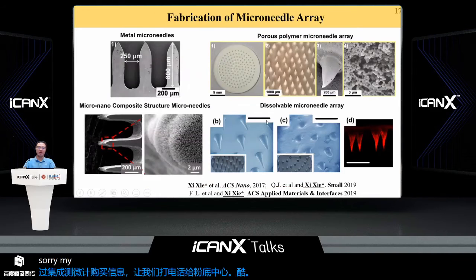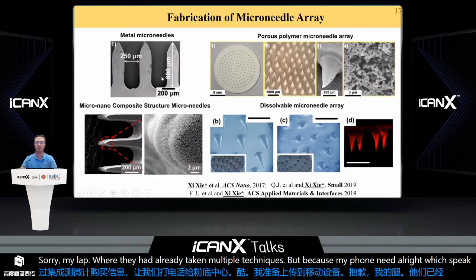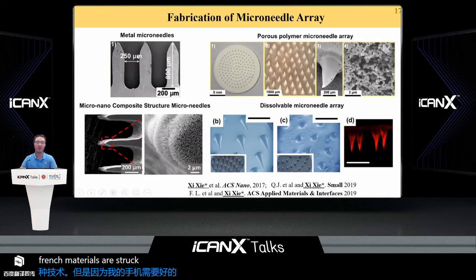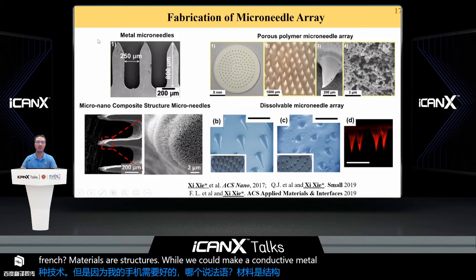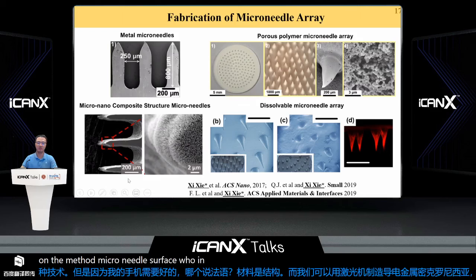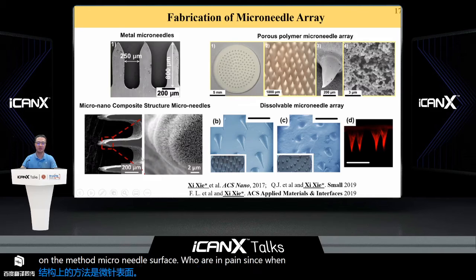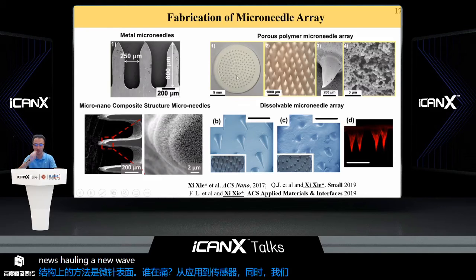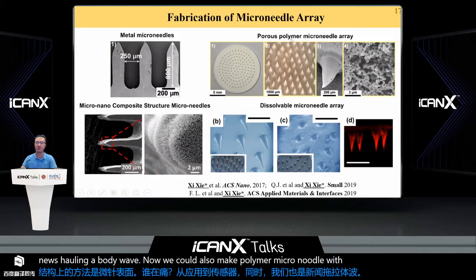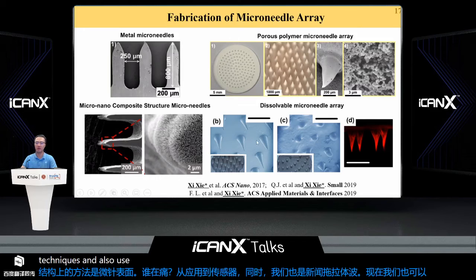So in my lab, we have already developed multiple techniques to fabricate microneedle arrays with different materials or structures. For example, we could make conductive metal microneedles using laser machining. We could also fabricate functional nanostructures on the metal microneedle surface to enhance the detection sensitivity when applied as sensors. Meanwhile, we could also make polymer microneedles with nanopatterned structures using a molding technique, and also use degradable polymer to prepare microneedles.